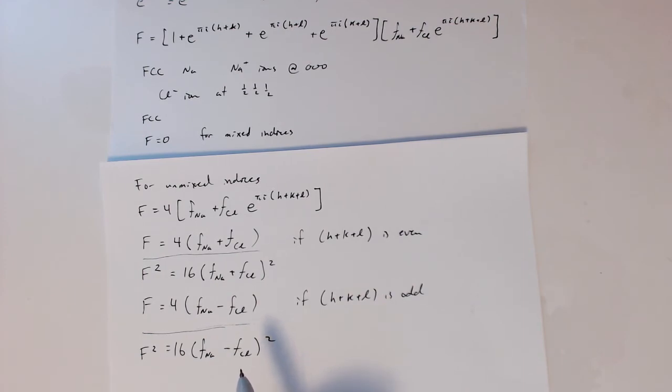So we can relate it to an FCC Bravais lattice in the structure factor calculations, and then just act like it has multiple ions per lattice point. Effectively, there are 2 ions, a sodium and a chlorine ion, per FCC lattice point. So that's the idea here. And that means that we have the same reflections, but there are some differences in the intensity in those cases.